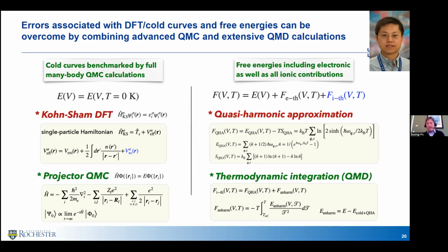QMD calculation. Why do you need a QMD calculation? Because in order to figure out the phase transition boundary, you need to know the free energy of the system in these two phases. Right? So the total free energy is the cold curve plus the electron entropy plus the ionic entropy. So he used the quasi-harmonic approximation plus thermodynamic integration, and you can get the ion entropy. By the way, the electronic entropy you can get directly from the DFT calculation.